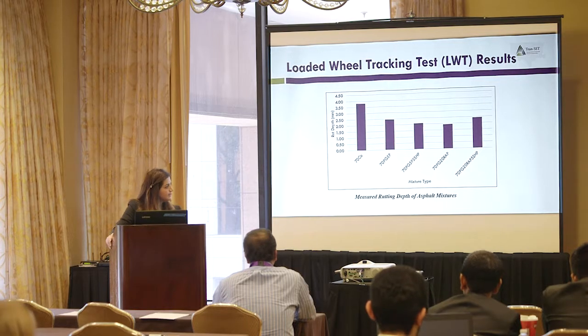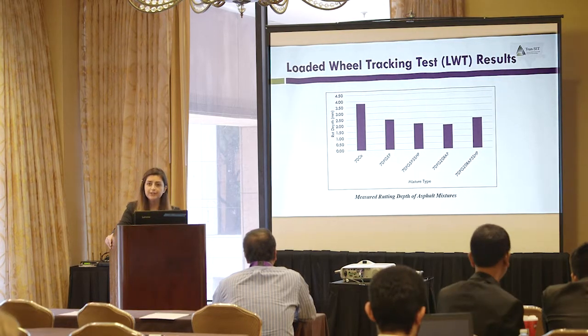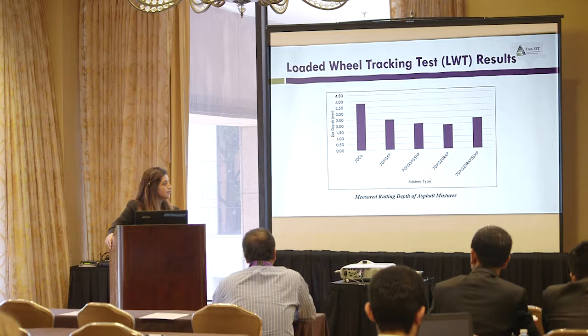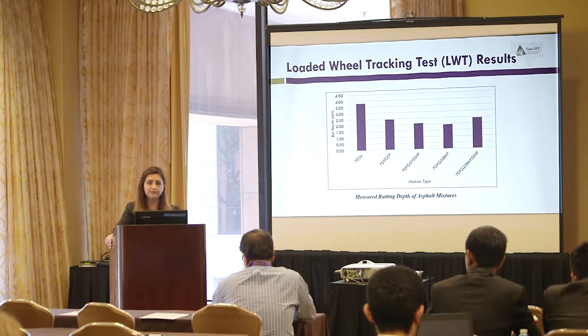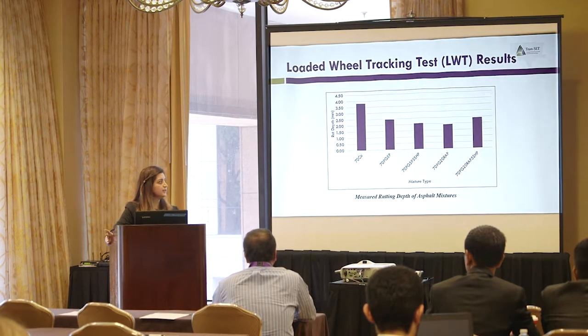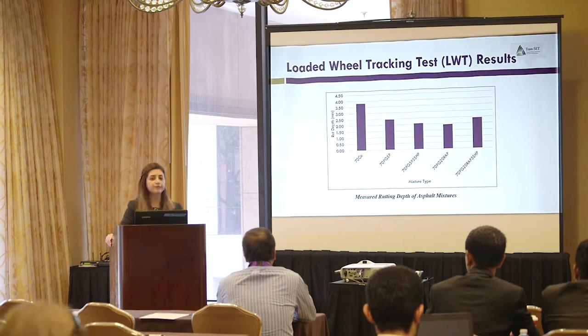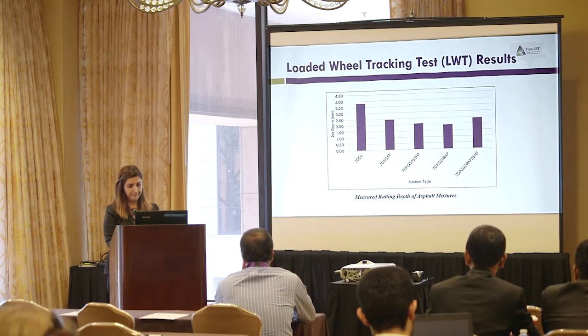For RAP, when we added 20% RAP to the mixture, we saw a decrease in rutting depth, but with addition of self-healing polymer, rutting depth was increased, but it's still within the criteria for Louisiana. Based on Louisiana specification, the rutting depth criteria is 6 millimeter, and we have something around 2.4 for the mixture with RAP and self-healing polymer.